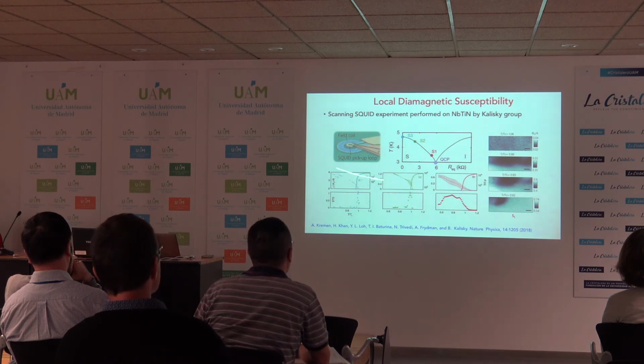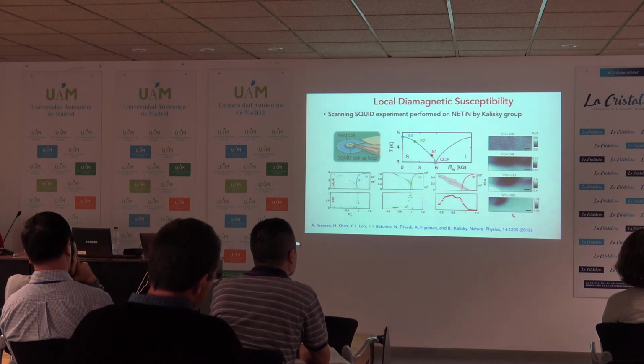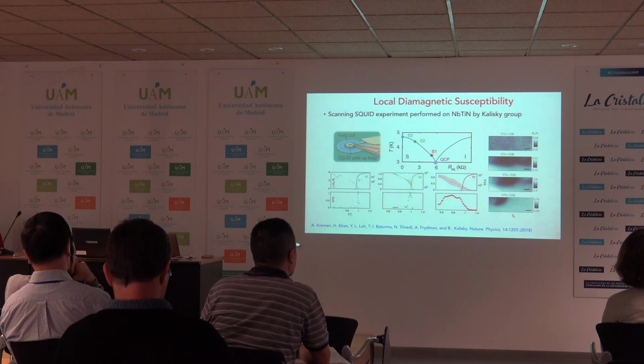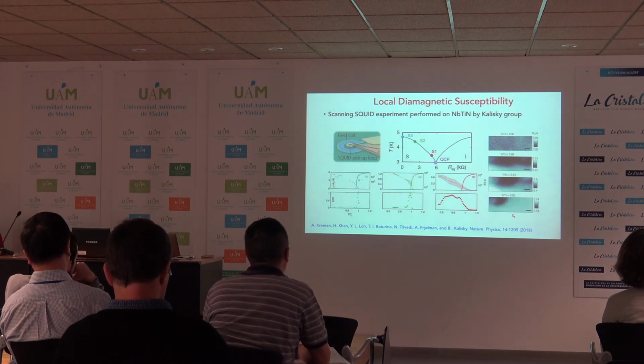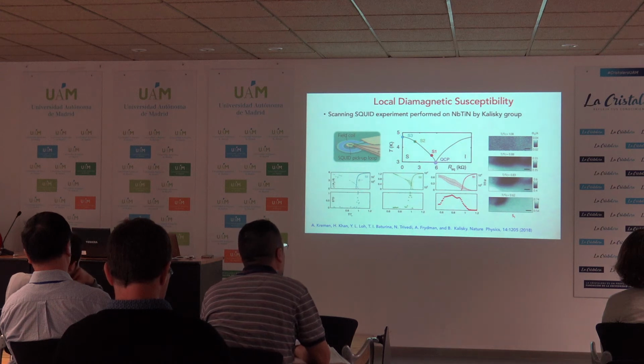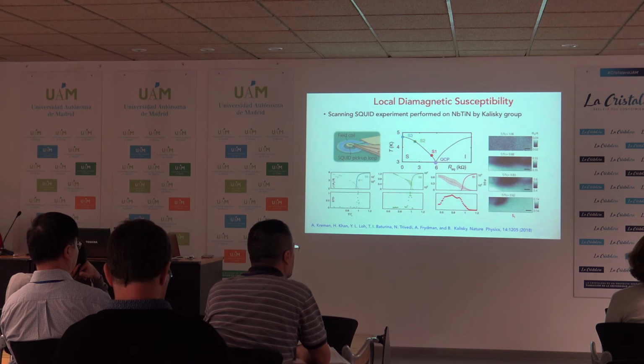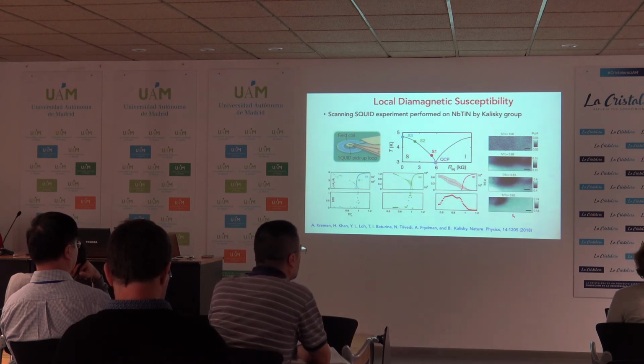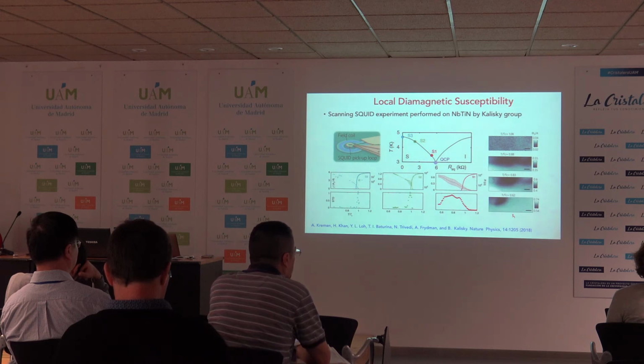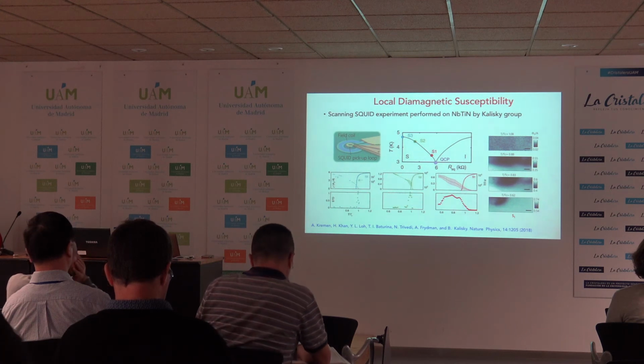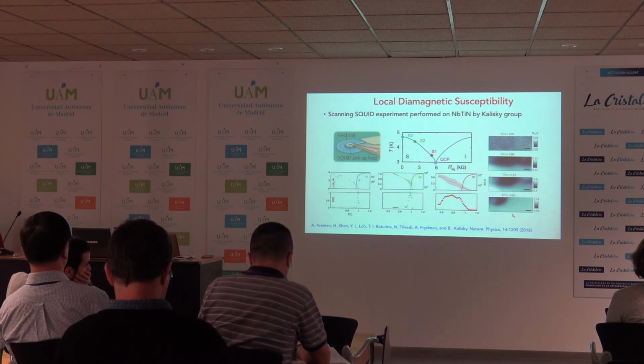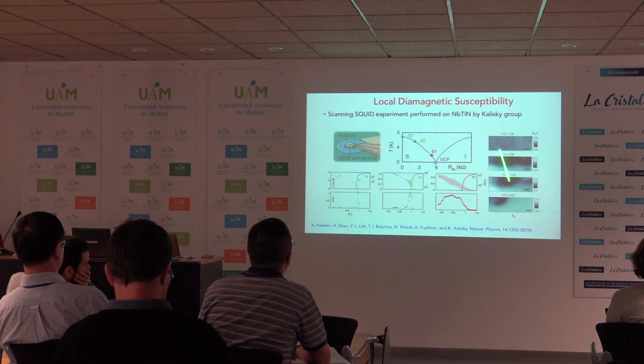And they can use this squid to pick up the susceptibility. So in a superconductor, the susceptibility ideally would be -1. Now the diamagnetism, because of these patches, is also patchy. Some regions are more superconducting. So now I'm not talking about the superconductivity within a patch, but the connections between the patches drive supercurrents. And these supercurrents would give you diamagnetism on the scale of microns, and they can do this sort of scan squid measurement and map out the distributions of the susceptibility. And what they find is, so these are 3 films. Again, it's being tuned by disorder.